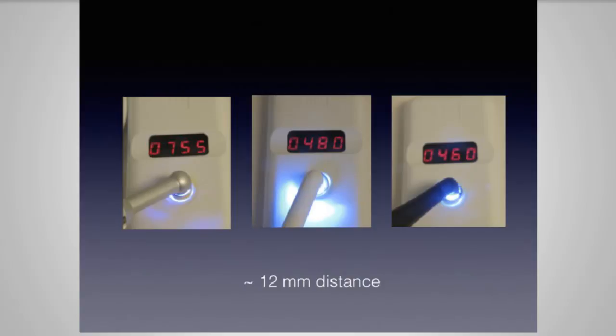The more you understand that light intensity and the ability of your light to really give good energy to the composite matters, the better, because otherwise the overall activation system is not going to have a chance to do its job deep down into the preparation. That is also why, if you're not using a bulk material, don't cure more than 2 millimeters at a time. And if you are using a bulk fill material, remember that you want to cure it 4 millimeters at a time, because otherwise the physical properties and the energy able to cure the material are going to be problematic, and you're going to have exquisite failures.